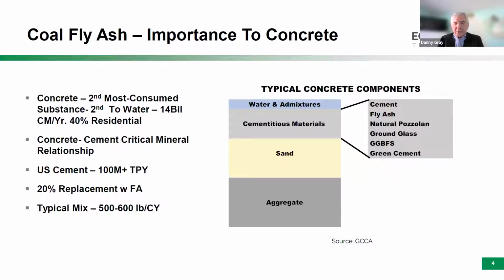If you think about concrete in the diagram there, you basically have four major components: the cementitious component, which is either cement or one of those subsets that you see to the right, and within a cubic yard of concrete, you have sand, aggregate, water, and some admixtures. Typically the cementitious component is going to be 500, 600 pounds on average per cubic yard of concrete. And what happens is that you can take out about 100 pounds of the cement and replace it with 100 pounds of fly ash. In general, that's just a quick summary of it. Next slide.